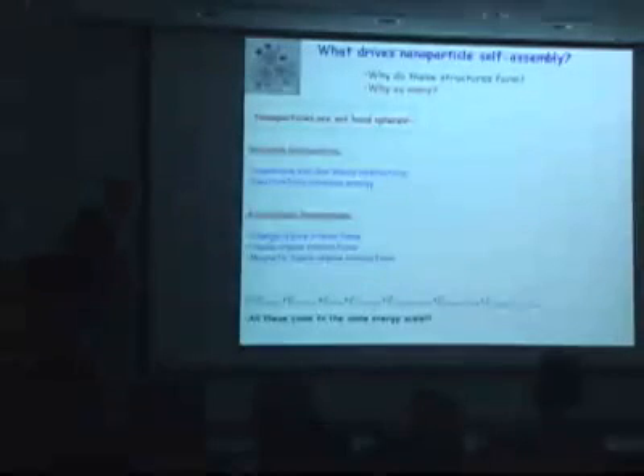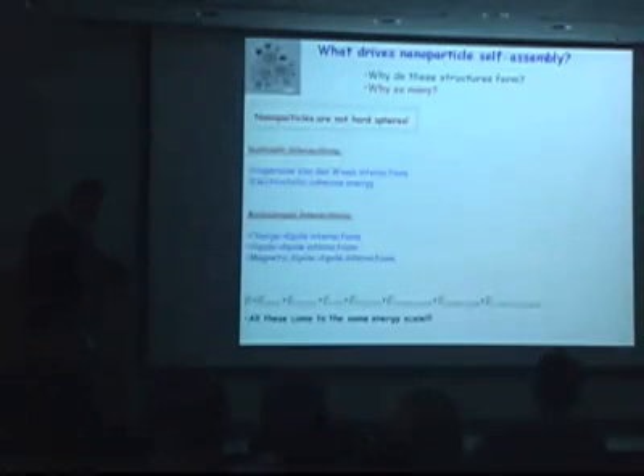This observation somehow defied traditional expectations and prior theoretical works in the field of sphere packing, because the outcome of theoretical calculations was that if particles were hard spheres, then only 3 binary structures should be thermodynamically stable against phase separation. And it's definitely not happening. So for us, the big challenge is to understand, with a reasonable level of detail, what is this magic force that brings 2 types of particles together and packs them into very complex arrangements.